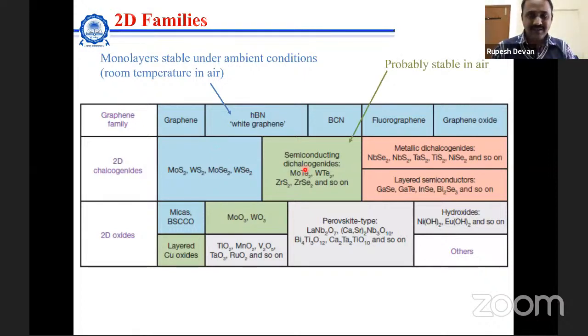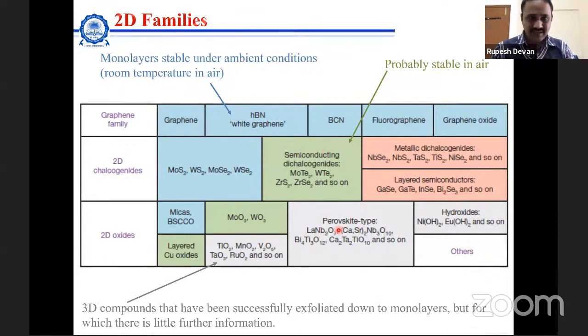But if you look at this color, they're probably stable, but not much data is available, because if you look at this particular oxide, they can reach an unstable state. So people are thinking that they may be stable at ambient atmosphere. But these are three-dimensional compounds, and not much data is available on this, because if you look at the example of titanium dioxide, they are always grown in the form of quantum dots or one-dimensional structures. Very rarely they are observed in two-dimensional forms. So people are trying to create two-dimensional structures for all these materials, and not much information is available about them.